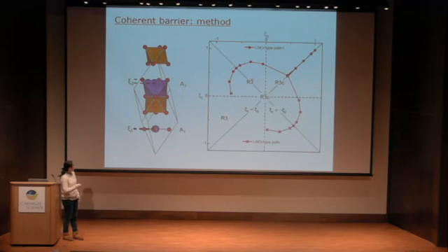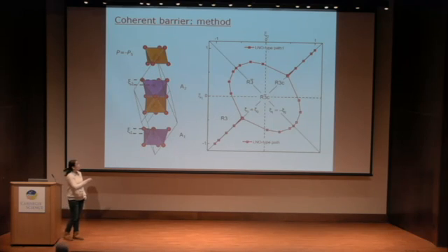Okay, and now the A1 cation moved downward. And now we are at the structure where the polarization is reversed. So, a summary: we're going from the red top all the way to the left bottom, driven by an unstable polar mode. But starting here, there is an unstable nonpolar mode that makes these two A cations move, one first, another follows. That's why we have this bubble inside, and that's why the energy barrier is lower here.